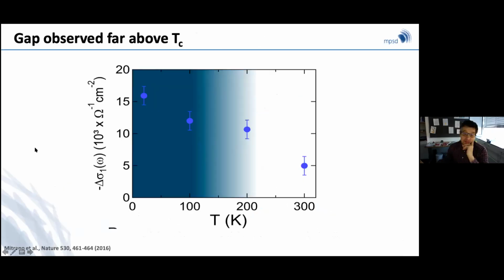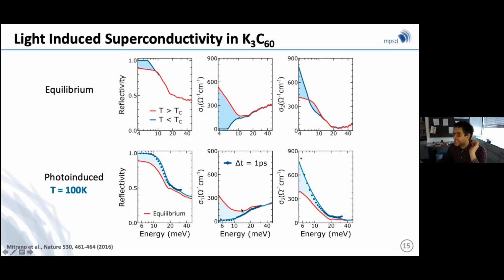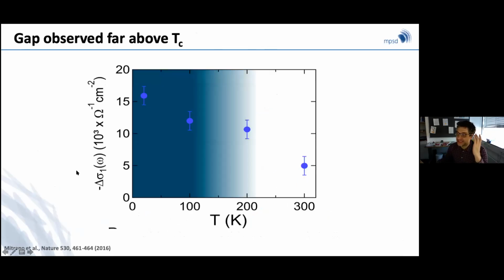The other very good thing, before I start raising all the questions and all the problems that these observations are causing, is that, as I mentioned before, you can plot now some sort of figure of merit. You can decide that the size of this gap is a figure of merit of the strength of my superconducting state or superconducting-like state. And then you can plot this integral as a function of base temperature. Remember, equilibrium TC is approximately 20 Kelvin. And then you can convince yourself that there's a very good gap.